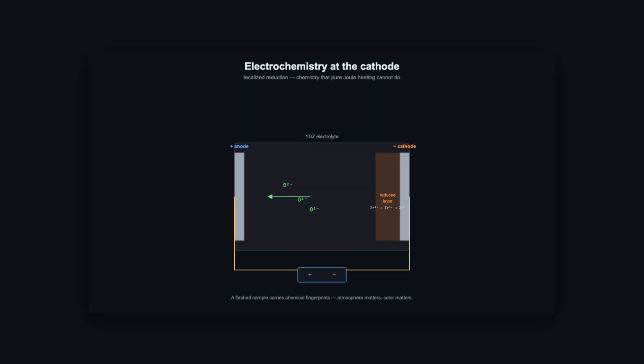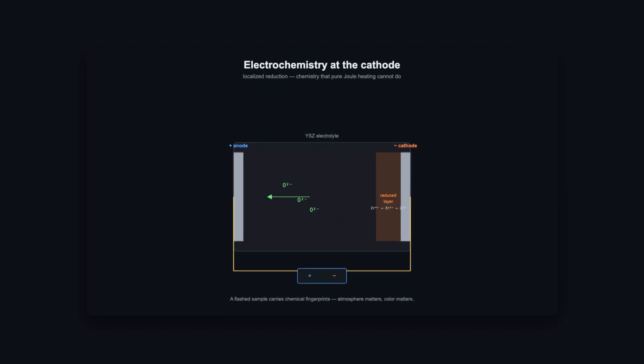The Raj side responds in kind. Hasan Naik and Marco Cologna have shown evidence of localized reduction at the cathode, chemistry that Joule heating alone cannot do. Samples flash-sintered in argon look different from samples flash-sintered in air. The microstructure carries fingerprints of an electrochemical event. Pure thermal models, the Raj camp argues, cannot reproduce those differences.